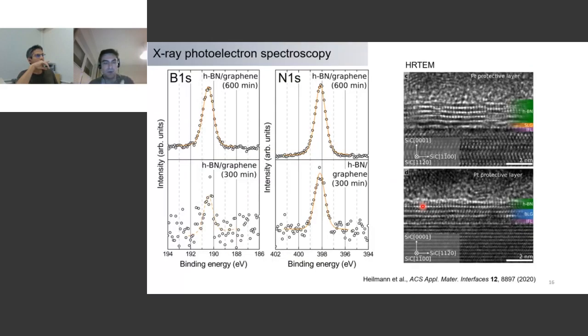We move on in the characterization to other techniques like XPS, X-ray photoelectron spectroscopy. What you do there is go to the boron and nitrogen 1s core levels to see if you get a boron and nitrogen signal, and we do get it. According to the binding energies, we can infer that we are forming the hexagonal phase and not cubic boron nitride. But still, of course, this is not the ultimate proof. In addition to that, we did a lot of TEM investigations where we can see that we have hBN layers that are, of course, defective, as you can see here, but they are forming on top of single layer graphene in this case, or bilayer graphene.